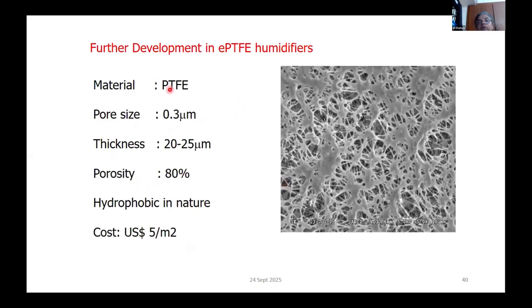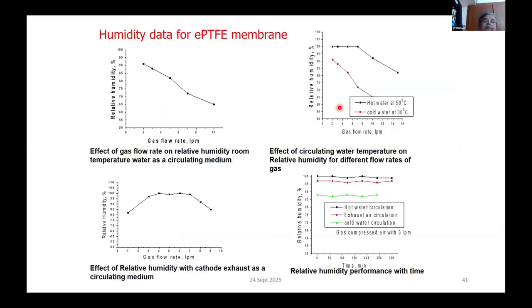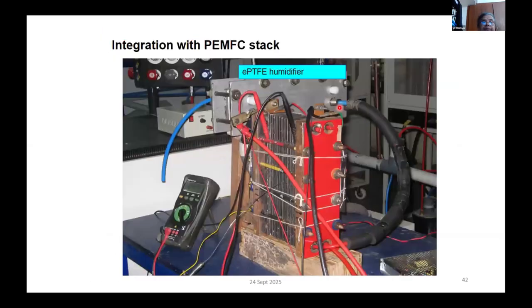So for such kind of humidifiers, you use expanded Teflon based membranes actually. These have more than 80% porosity, and these can be used for making these kinds of humidifiers. And again, you have to size your humidifier according to the amount of gas that you are giving. So you study with respect to the flow rate, what kind of humidities you can get, and with respect to temperature, what kind of outlet temperature you are getting from your stack. Based on all these things, you can size your humidifier. And then finally it is integrated. This is a PEM fuel cell stack, and this is a humidifier, and we integrated it for performance studies.